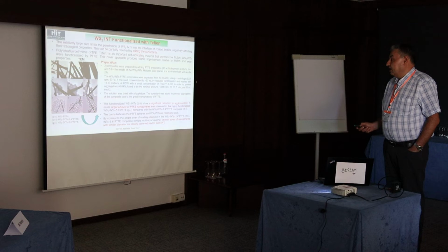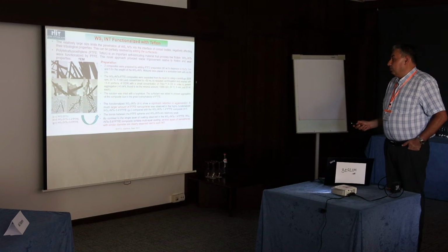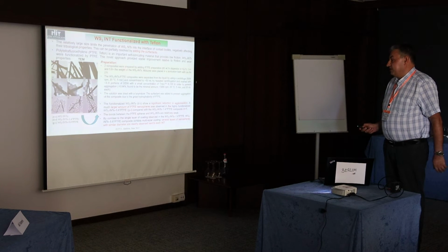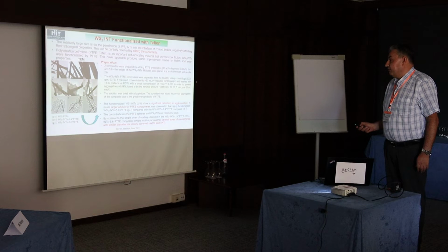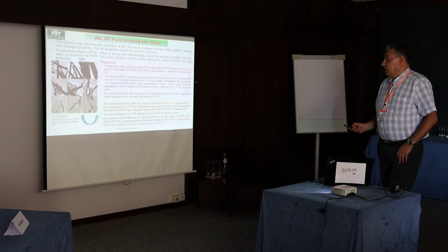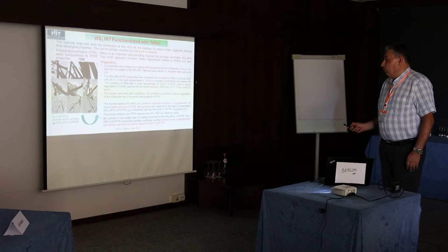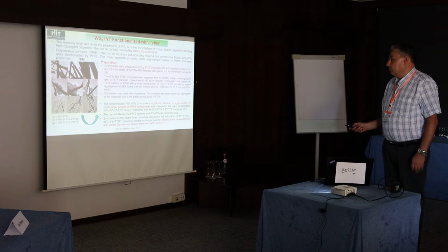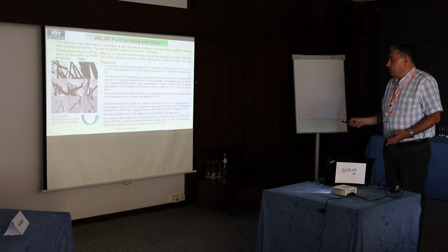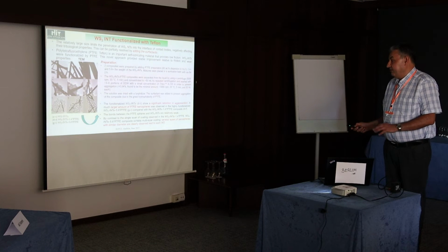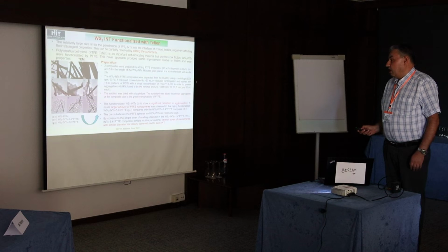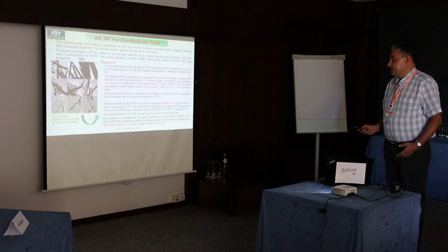So this is the preparation procedure. We use two types of samples with different concentrations of Teflon relative to WS2, 1.4 weight% and 5.6 weight%. The procedure was quite complicated, but finally we got our materials covered with Teflon.